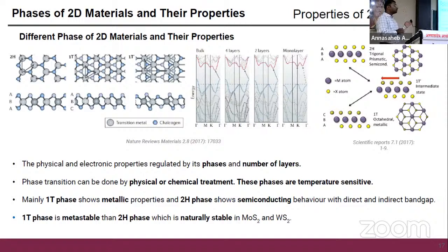So if we consider the 2D TMDC materials, there are basically a few phases, which are known as the hexagonal phase and tetragonal phase in the case of TMDC materials. So the hexagonal phase is considered to be a semiconducting phase of these TMDC materials, and the tetragonal phase is considered to be the metallic phase. Naturally, the 2H phase is very stable for these materials because it is thermally stable, and 1T is metastable or a little bit unstable. So depending on how the bonding is, this structure is defined. If there is hexagonal arrangement, then hexagonal. If there is tetragonal arrangement, then there is tetragonal structure.